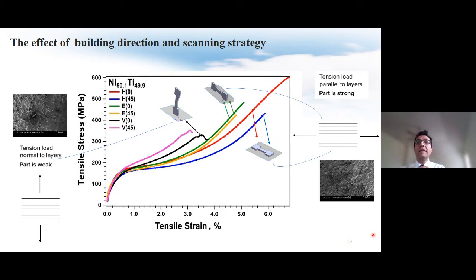By the way, we found that the influence of the building direction, I mean horizontal or the vertical one, was significantly higher than that of scanning strategy. For the specimen built vertically, when we look at the SEM image at the failure, we observe that the type of the failure was interlayer failure. On the other hand, in the case of the horizontally fabricated specimen, such failure was not observed, and that is why higher strength was observed.